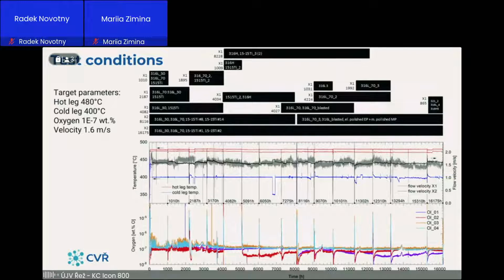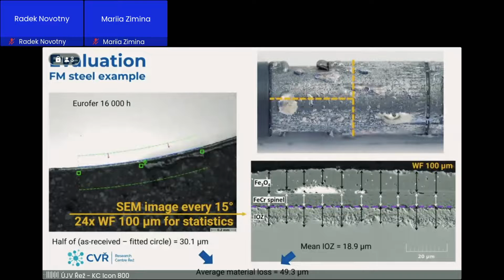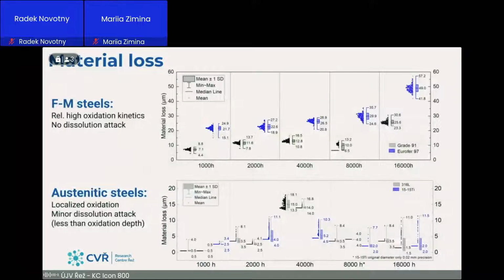Here is also a record of temperature, it's 480 degrees C. There is also a record of flow rates in each leg and a record of temperature in the cold leg. So evaluation of specimens was done on metallographic cross-section. We fit the diameter circle on the metallographic transverse cross-section, and also do some characterization in a systematic way around the perimeter of the specimen to calculate the thickness of the features that were on the perimeter. So the result is here.